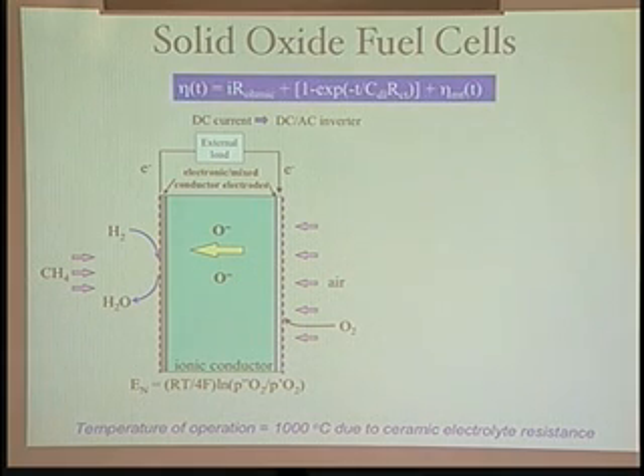Okay. Now we get into a bit of the technology. If you look at the polarization or the losses in an electrochemical device like this, there's an IR term or an ohmic term, which is basically just the resistive drop across this membrane. And there's a charge transfer term, which is essentially what's happening at the electrodes, and it has to do with how fast that reaction occurs. And there's what we call a mass transfer term, which is how fast the gas goes through the electrode. At these temperatures, that's generally not a problem. So how do we get the temperature of this fuel cell down?